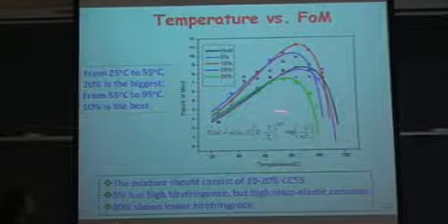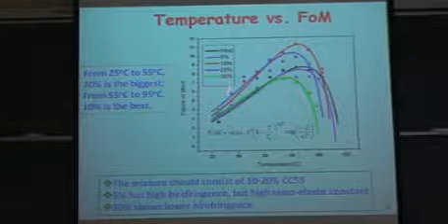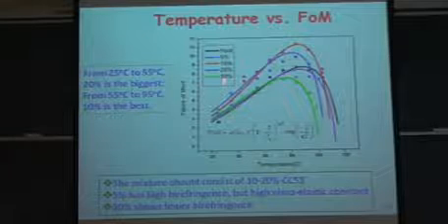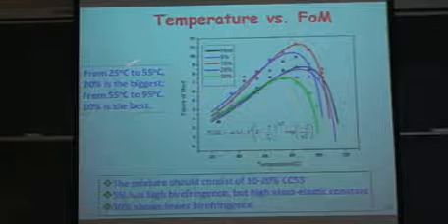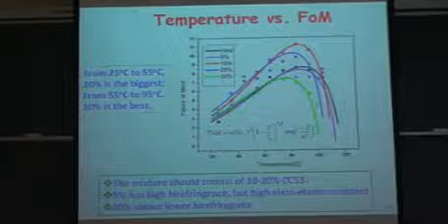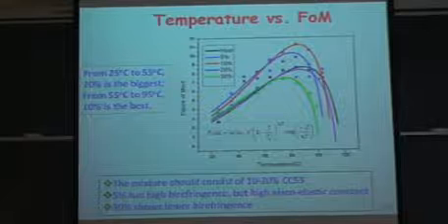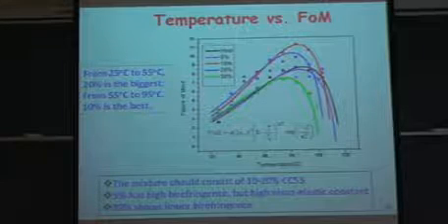So this is the viscoelastic figure of merit. Consider both the birefringence and the viscoelastic constant. We can see at room temperature, in this region from 25 to 55 degrees, the blue line is largest, so 20%. And at high temperature, from 55 degrees to 95 degrees, this red line is best, so 10% is best.